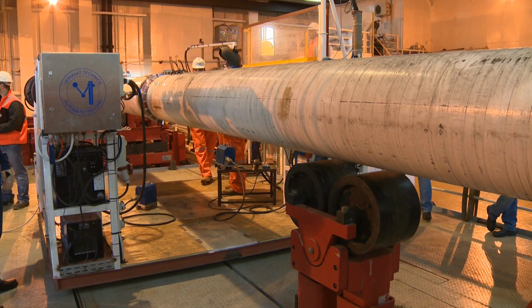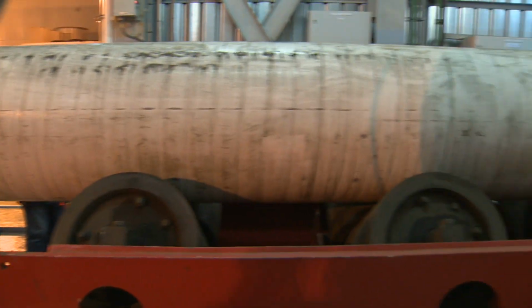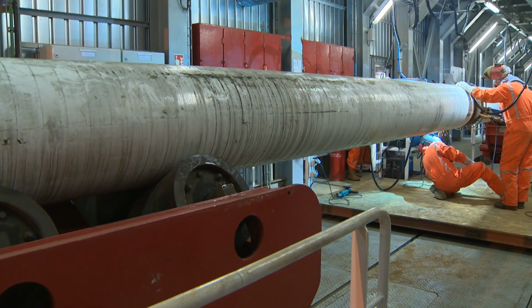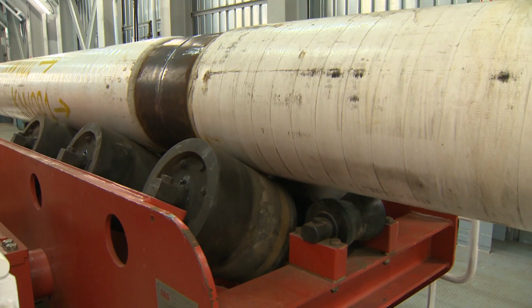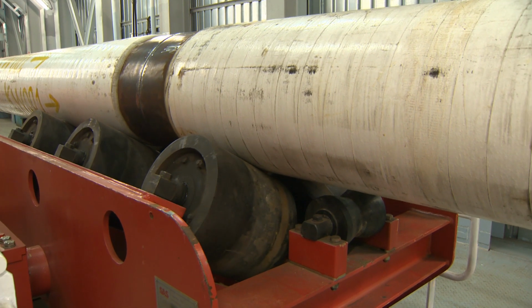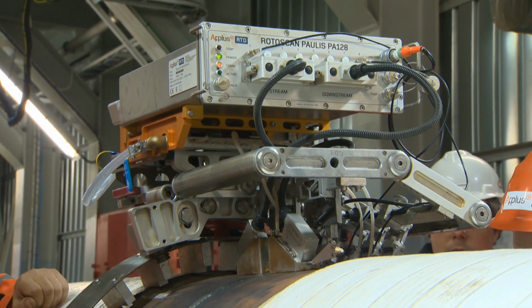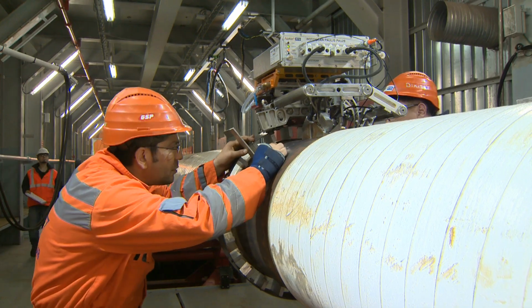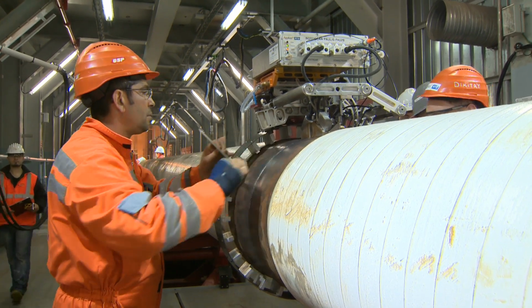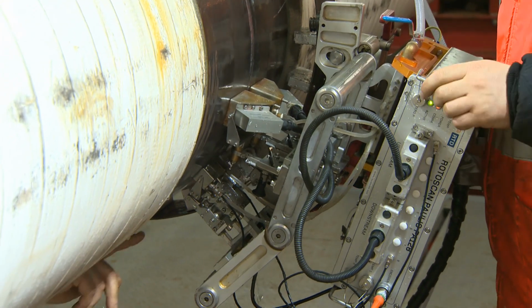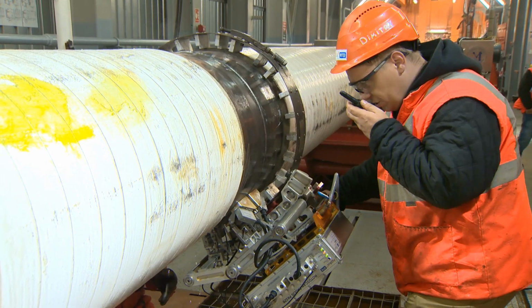No matter how thorough the job is done at the welding stations, there is always a risk taken into account. This is why the pipe goes to workstation 4, where a non-destructive ultrasonic testing is performed. The QC team inspect the welding for gas bubbles, lack of penetration, lack of fusion, porosity or cracks, for example.